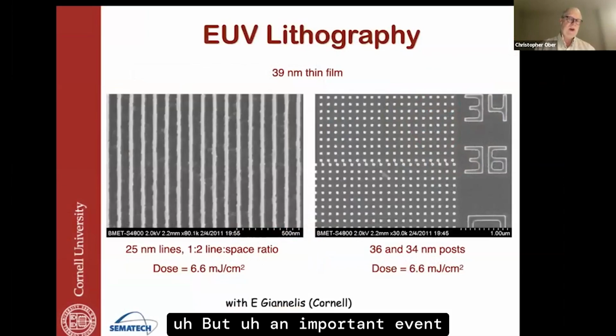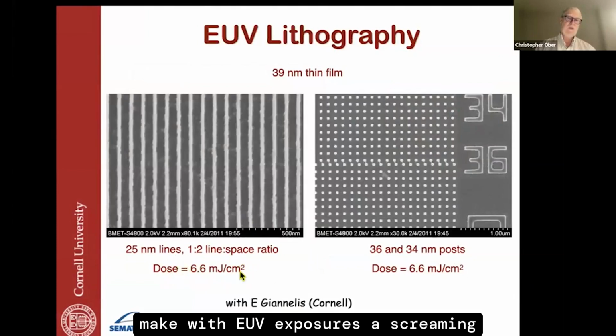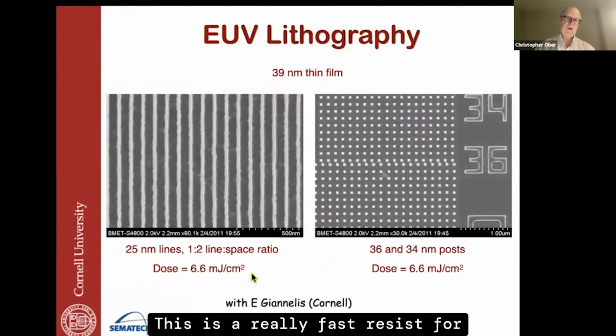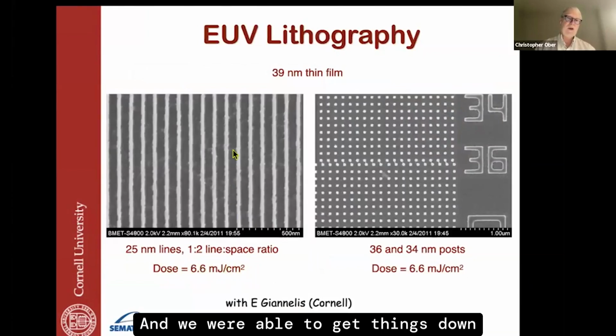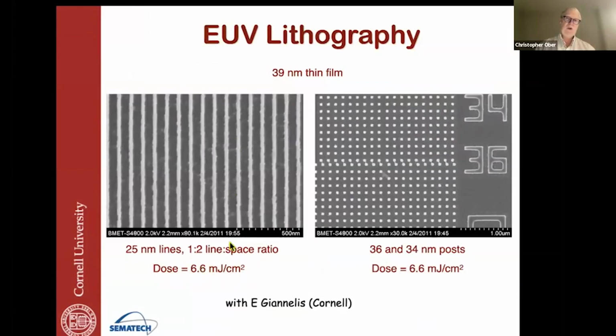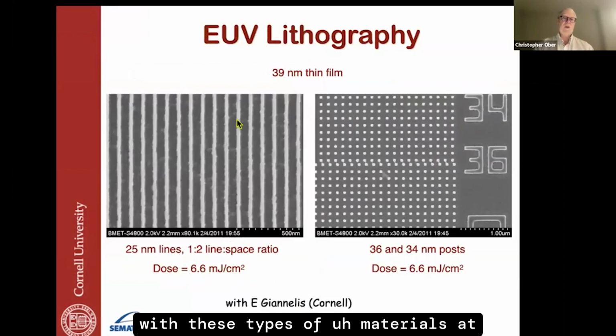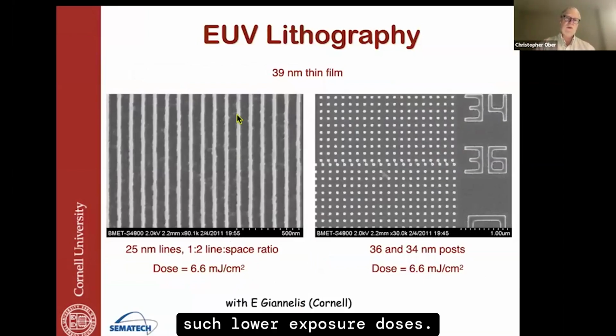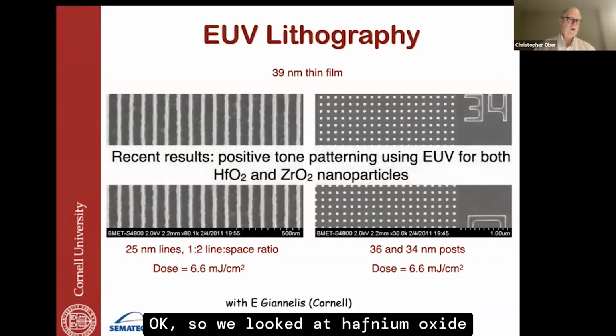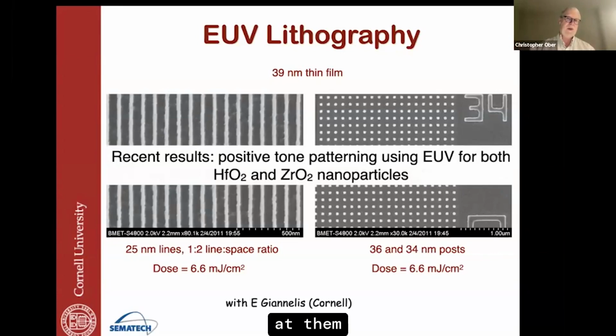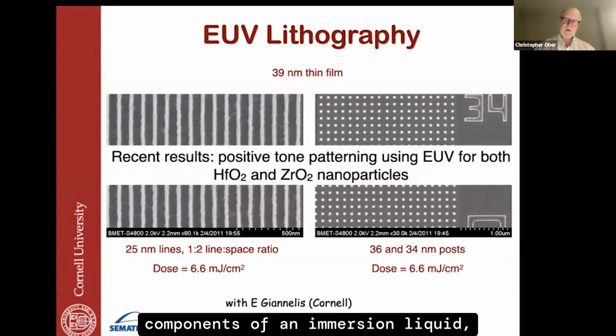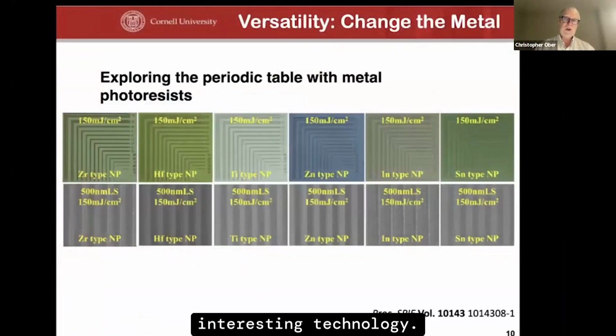But an important event occurred when we demonstrated that with these nanoparticles, we could make, with EUV exposures, a screaming fast photoresist. This is a really fast resist for EUV. And we were able to get things down in the 25 nanometer regime, which had never been done before with these types of materials at such low exposure doses. And so this really reopened interest in advancing these types of photoresist. Okay, so we looked at hafnium oxide and zirconium oxide. They're poorly absorbing at EUV wavelengths, but remember we originally looked at them as high refractive index components of an immersion liquid, not a bad repurposing of some interesting technology.